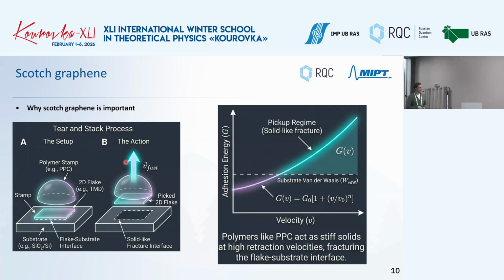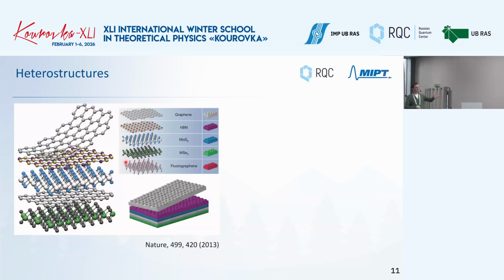The reason is the following: it turned out already in this review in 2013 that you can have different 2D materials and put them on top of each other. Because they are flat, you can put them on top, and because they interact via van der Waals forces, you can detach them. Van der Waals forces are very important because they are not very strong, and with these stamps, Scotch tape and so on, you can tear off the bulk material to get to the monolayer limit. And then when you have different types of flakes, you can put them on top of each other and play with the properties.